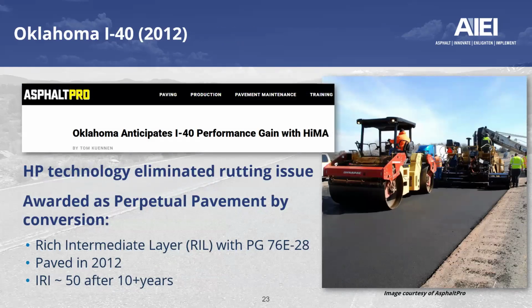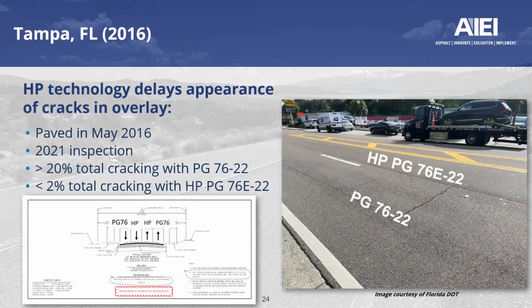Another interesting project goes to Oklahoma on the I-40 in 2012, and the use of such technology eliminated the rutting issue, and it was awarded as a perpetual pavement by conversion. Later in this presentation, we'll talk about the rich intermediate layer, the RIL, a type of mixture being used by Oklahoma DOT with an HP binder. Again, that section was paved in 2012, and it shows an international roughness index of 50 even after 10-plus years.